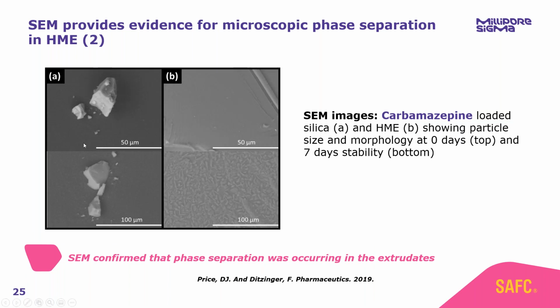Same was true for carbamazepine. We had no change from the fresh to the 1 week sample for silica, but for the HME formulation, we went from a totally smooth homogeneous surface to a non-smooth heterogeneous surface. And if you can see that, it's starting to look like crystalline structures on the surface of that polymer. So we no longer have the immobilization within a polymeric matrix. Our molecules are forming API-rich domains via phase separation. And as we discussed, we've just given the molecule the opportunity to recrystallize.